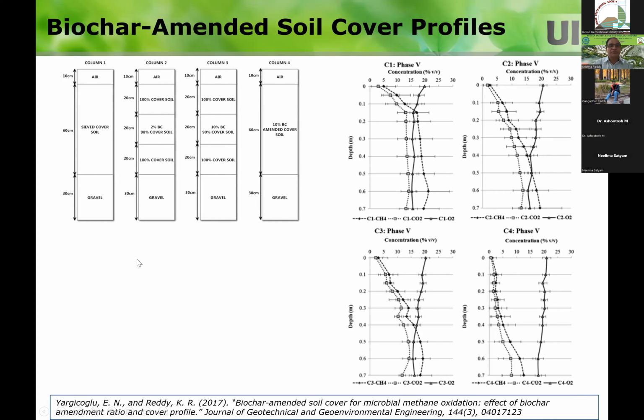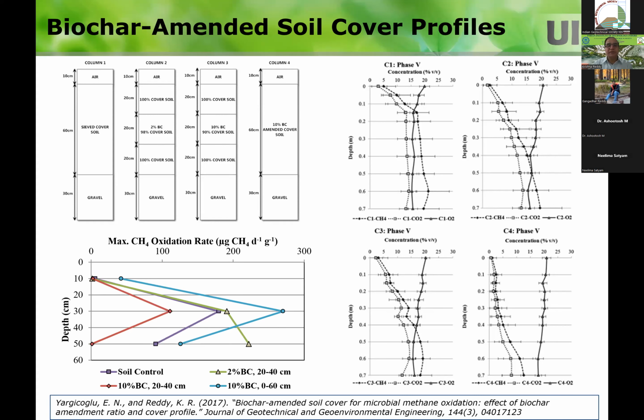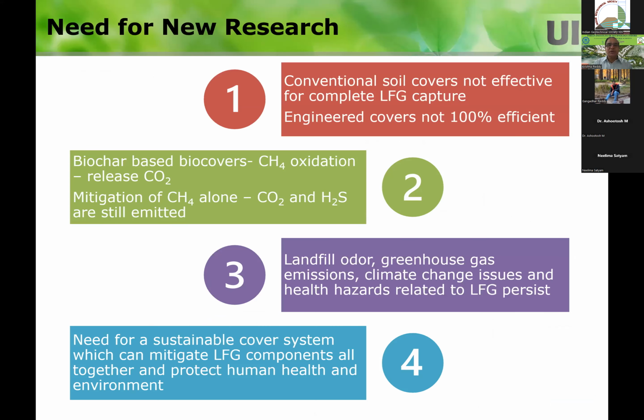And then again, like what I showed you in the previous slide, we would inject the simulated landfill gas from the bottom, and we look at what is happening along the depth. So you are looking at these profiles. This is cell 1. The concentrations are high across the profile. But if you look at the last one, this is the 10% biochar amended, you can see the concentrations are very low because the methane is being oxidized. So clearly, we could show that the biochar amended soil will have a significant increase in methane oxidation. Okay, so those were initial studies.